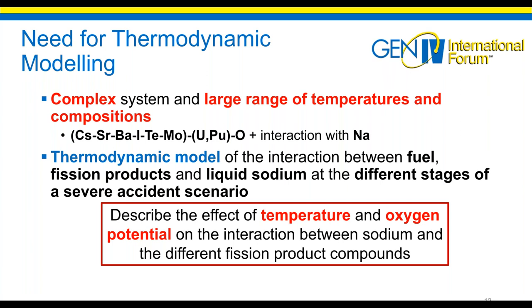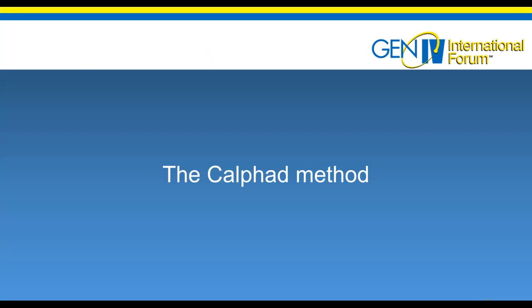3000 degrees C. Therefore, there is a huge need for thermodynamic modeling of the interaction between the fuel, fission products, and liquid sodium at the different stages of a severe accident scenario. In fact, the final goal is to describe the effect of temperature and oxygen potential on the interaction between sodium and the different fission products compounds. Because in fact, these two parameters are key factors for the phase formation in the systems. And to develop this thermodynamic model, we will use the CALPHAD method.